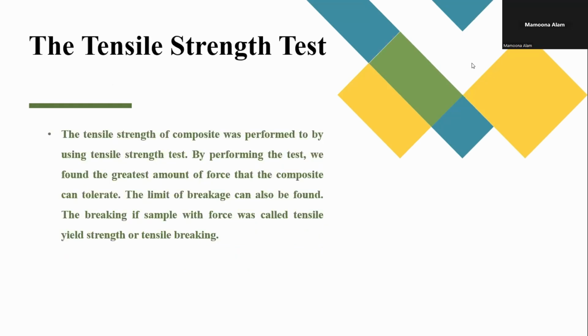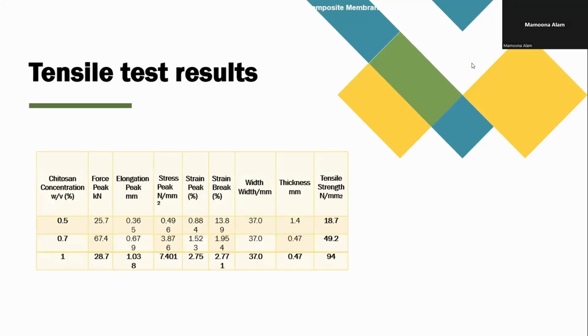Then we sent our membrane for tensile strength testing. By performing the test, we found the greatest amount of force that the composite can tolerate. If we increase the amount of chitosan in the PVC membrane, it increases the strength, and the limit of breakage can also be found. The breaking of the sample under force is called tensile yielding, or yield strength, or tensile breaking. These were the results sent by the laboratory for three different membranes with different chitosan concentrations.